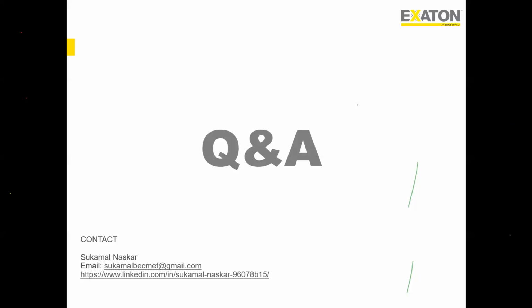Yeah, thanks. Now another question: what is the minimum allowable ferrite percentage in hyper duplex? For any duplex family, the requirement comes from codes and standards. If I take API 582, one of the most commonly used codes, the weld metal is 30 to 65% ferrite. For base metal we don't need to worry, because hyper duplex base metal is one of the most balanced structures, almost 50%. The challenge comes on the weld metal, but we have done several welds on hyper duplex. It is always on the higher side of ferrite, but it can be managed within 45 to 65% ferrite. So there's no problem on that.